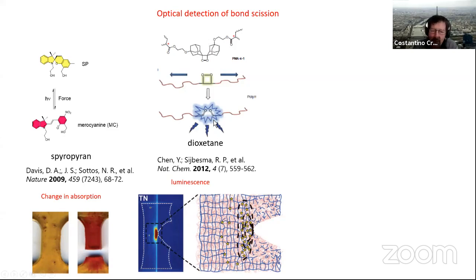But we used this molecule successfully to actually detect in real time the breakdown of sacrificial bonds in a multiple network elastomer, something inspired by the double network gels of Jian Ping Gong. And we could really map for a given sample regions where there was a high level of bond breakage at any given time, or a low level of bond breakage. So in a way, a relative quantification.